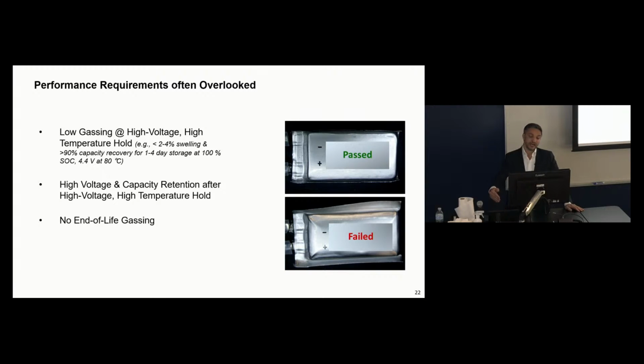In addition, if you have this high voltage, high temperature hold, it has to retain not only capacity, but also has to retain high voltage. If the impedance rises, if the voltage becomes smaller, it's a huge problem. And certainly there should be no end-of-life gassing. So when the battery dies, you don't want it to explode. And this becomes very critical, particularly for automotive cells that have to last for decades.